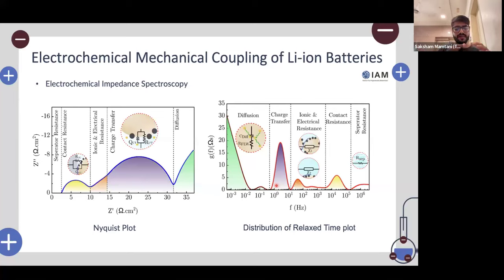So a typical analysis of the EIS is done in two ways. We have the Nyquist plots and we have the DRT plots, or the distribution of relaxation time plots. The output of these plots is going to be curves with peaks and lows. And each peak and each low contributes to a different electrochemical phenomenon that is taking place inside the battery.